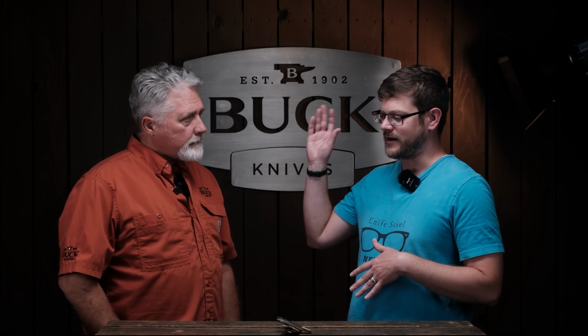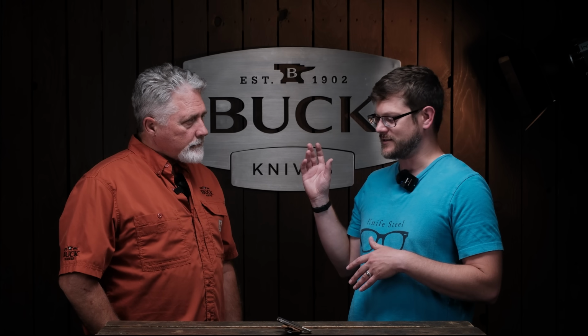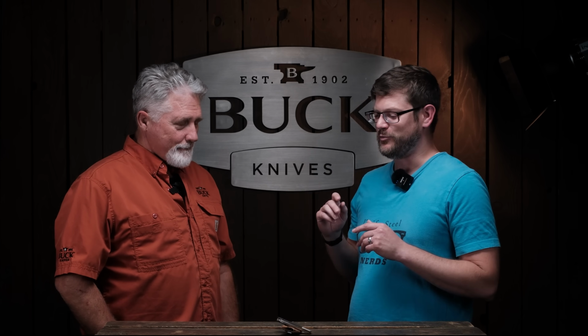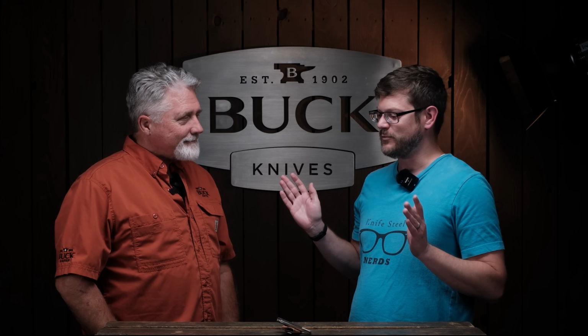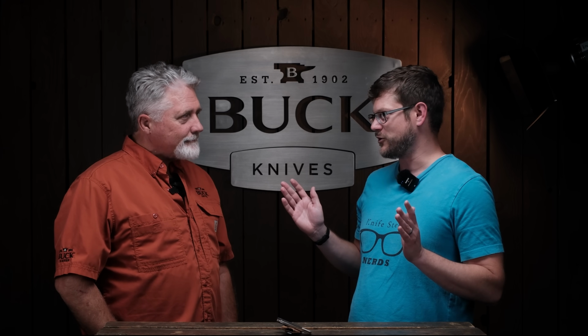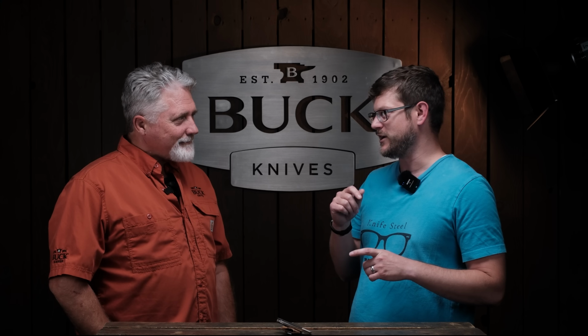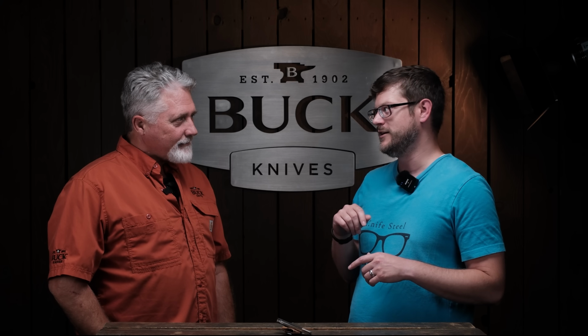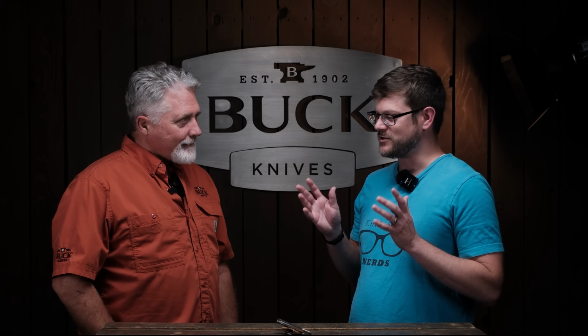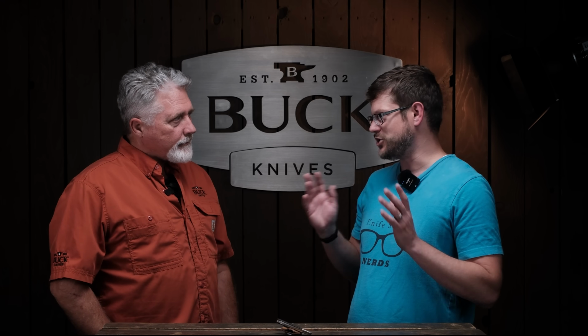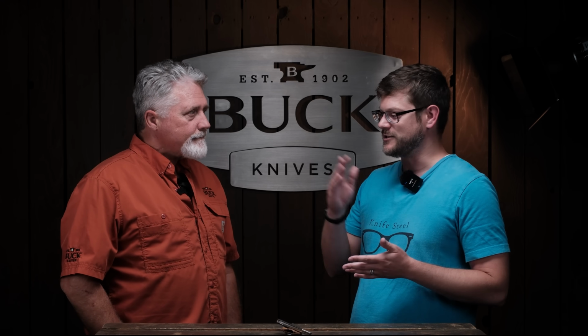So we heated it up hot, and when it gets hot, it turns to a new phase called austenite. So that's a fancy term. Yep. But this is really easy to see. Bladesmiths know all the time when it transforms to austenite because you can use a magnet, because austenite is non-magnetic. So this is an example of transformations that can occur in the steel and really change its properties. Okay. It goes from magnetic to non-magnetic.